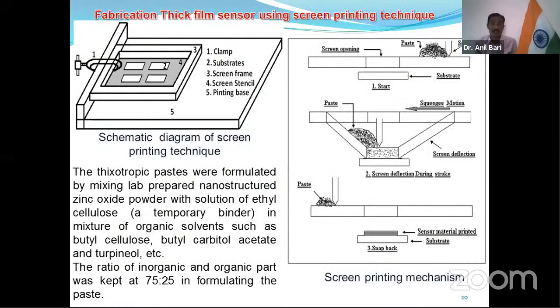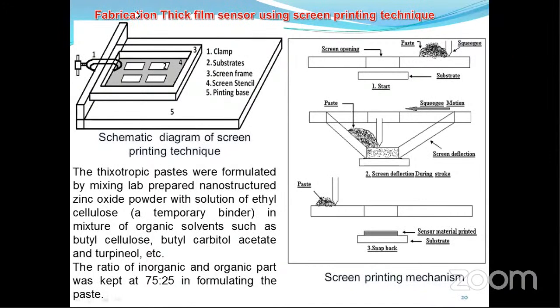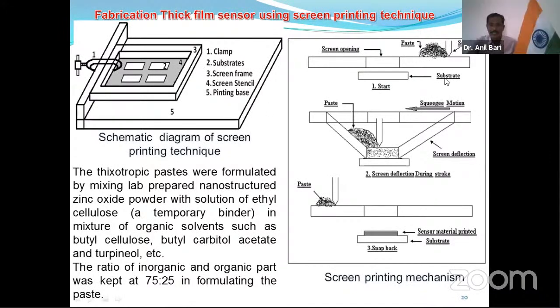Now, this is the fabrication of the thick film sensor using the screen printing technique, which is simple. We can prepare this powder thick film with the help of the laboratory. This is a simple screen printing technique, and this is a schematic diagram of it. The thixotropic paste was formulated by mixing the laboratory-prepared nanostructure zinc oxide powder with a solution of ethyl cellulose, which is called a temporary binder, and a mixture of organic solvents such as butyl cellulose, butyl carbitol acetate, and terpineol. The ratio of the inorganic to organic part was kept at 75 to 25% in formulating the paste. So this is a simple screen printing technique.